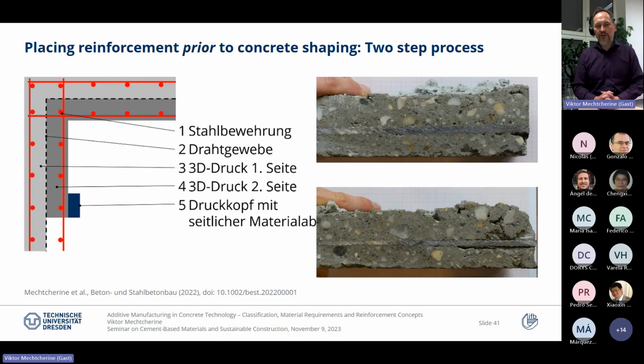Okay, now I come to placing reinforcement prior to concrete shaping. This would be a two-step process. The concept we suggested for steel reinforcement is, first, a cage of reinforcement placed here. You then have in the middle a very thin mesh just to control the material flow. And then you just deposit layer after layer from one side and then from the other side. We tested this approach in the lab, so it seems to work. It's not always great, specifically at the beginning of the printing process. We have some issues in enveloping the reinforcement nicely, but in general, it seems to work.